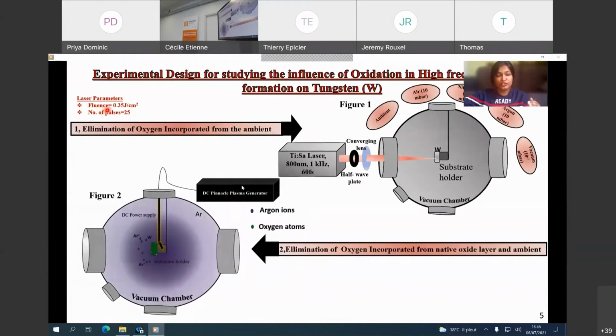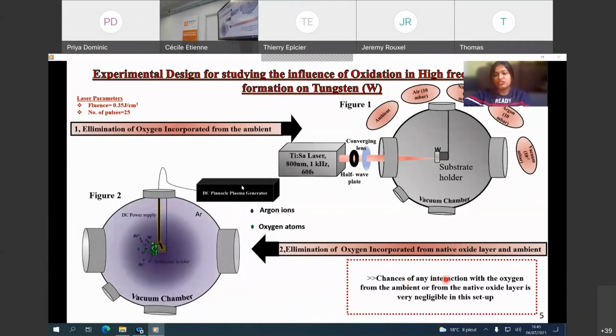So we use a fluence of 0.35 joule per centimeter squared and 25 pulses for all the laser irradiations. And we have 2 sections of experiment. The first section is without sputtering under 5 different gaseous conditions, and the second section is with sputtering under 5 different gaseous conditions. And the chances of any interaction with oxygen from the ambient or from the native oxide layer are very negligible in this setup.